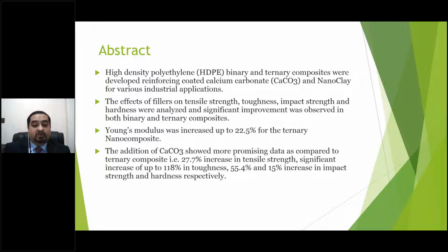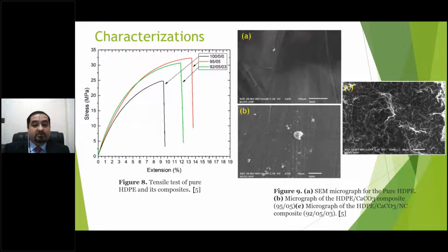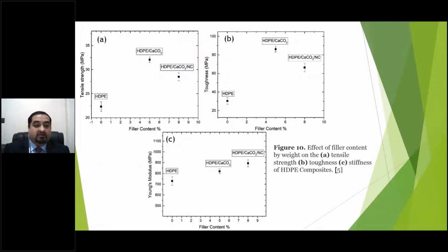And later on, we looked at the tensile strength, and we did find enhancement in those properties. Now here you can see 100% HDPE was compared with a 95:5 calcium carbonate based specimen and a 92:5:3 weight percentage of HDPE, calcium carbonate, and nanoclay. Uniform dispersion was once again achieved, and we did see enhancement in the mechanical properties by the incorporation of calcium carbonate. The same sort of results were obtained for tensile strength, toughness, and Young's modulus.